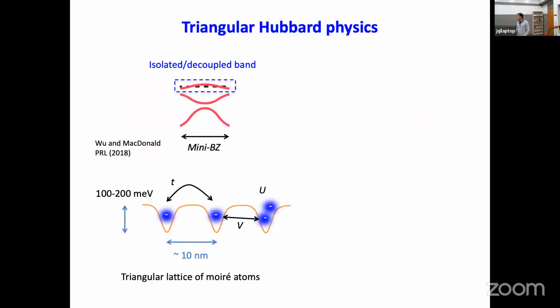Okay, so interestingly, it was pointed out first by Allan MacDonald's group in 2018 in a PRL paper that if you have a well isolated enough flat band in the system, say we only look at this particular band at the top of the valence band here, then the low energy physics can be mapped to a triangular lattice Hubbard model. The Moiré superlattice structure is a triangular lattice. The electrons are trapped by these artificial Moiré atoms. The typical trapping depth is 100 to 200 milli electron volts. The atomic spacing is about 10 nanometers now.